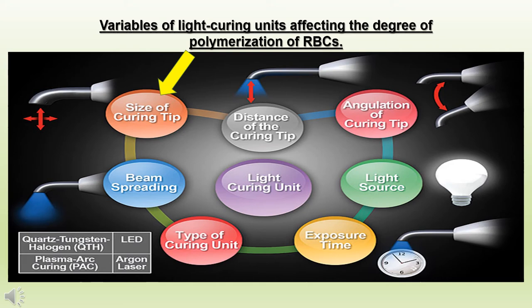Let us look at the variables in light curing units which affect the degree of polymerization of resin-based composites. The first one we'll be looking at is the size of the curing tip. LC units are available in 3, 8, 10, 11, 13, and 14 millimeters diameter tip. A light curing unit with an 11 millimeter tip has energy which is more scattered, whereas in a light curing unit with a smaller tip of about 3 mm, the energy is more focused and so less time is taken to cure, but at the same time more temperature is produced, which can be dangerous to the tooth pulp.